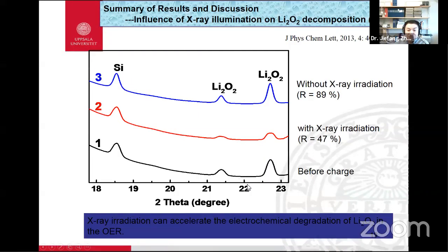The first experiment we did is to study the X-ray effect on lithium peroxide decomposition. So this is before charging. This is with continuous X-ray irradiation for 3 hours. This is without X-ray irradiation. We can see that under continuous X-ray irradiation, the decomposition speed almost doubled.